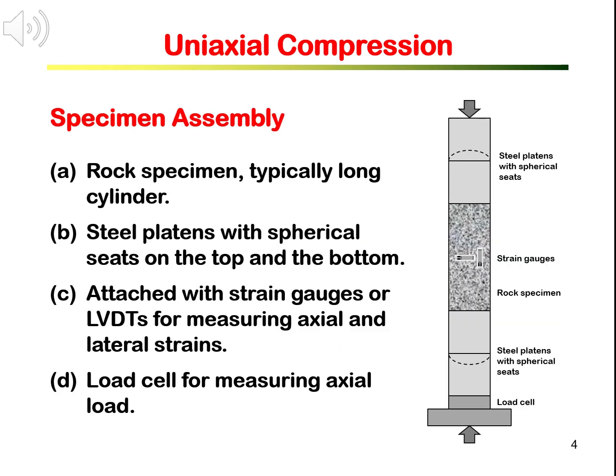In the ISRM suggested method, there is quite strict requirement on rock specimen assembly, particularly on spherical seating. Rock specimens are typically rock cores cut into cylinder with length 2 to 3 times the diameter. For example, if the core diameter is 50, the length should be 100 to 150 millimeter. The specimen should be sandwiched between hardened steel platens. The steel platens should have spherical seating. The spherical seating is to ensure uniform loading on the specimen in case the specimen ends are not parallel.